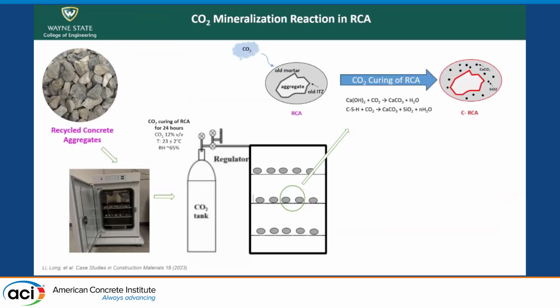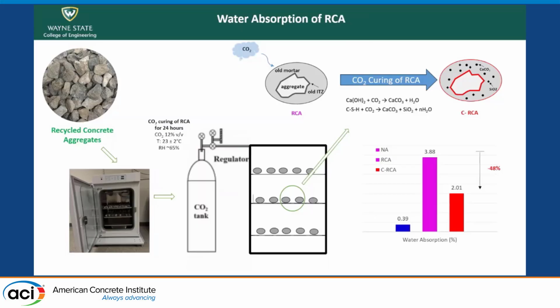In order to find a solution to make these RCAs better to use in our concrete, we went through this carbonation or carbon curing process. So the RCAs have attached old mortar in them. We have the aggregate, the old ITZ, and the old mortar. We induce CO2 in these RCAs, and the CO2 inside the carbonation chamber reacts with the already existing products in the old mortar to create calcium carbonate.